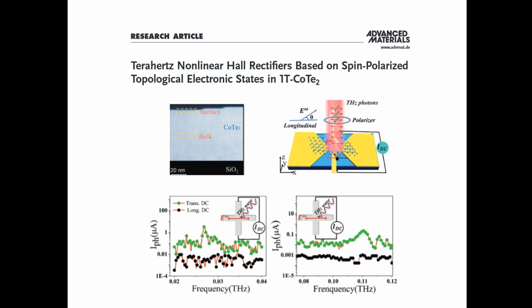And this is a recent experiment from China that showed that in this topological semimetal, cobalt ditelluride, the nonlinear Hall effect has indeed been observed even in the terahertz frequency range. Using an antenna to enhance the terahertz electric field, they find that a transverse DC current arises when the polarization is in the right direction, in the Hall geometry. But this goes away if the electric field is in the other direction.